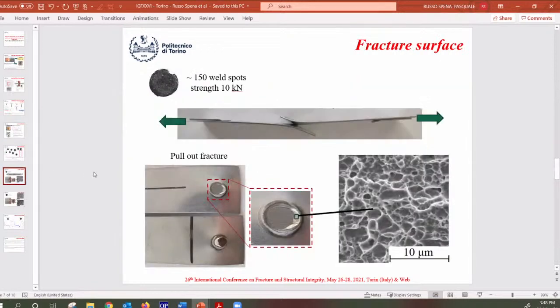Particularly here, you can see which was the fracture mode obtained after sound joints. Here, you can see the classical fracture of spot welds through a pullout fracture that is characterized basically by the fracture of the heat affected zone around the weld nugget with a traditional ductile fracture.